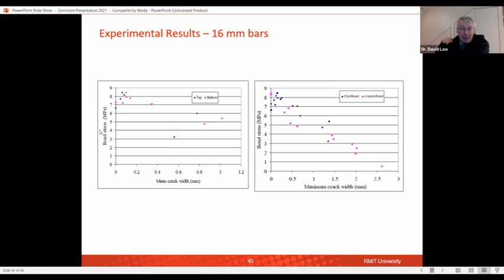And what you see, interestingly, is that when you start with corrosion, you actually get a bit of an increase in strength. And that's because that extra corrosion acts as extra ribbing and an anchor into the structure. But then once you get past that, you start to get a deterioration. In some cases, we get a very good relationship, and in others, it was nowhere near as straightforward as to what was happening sort of with those relationships.